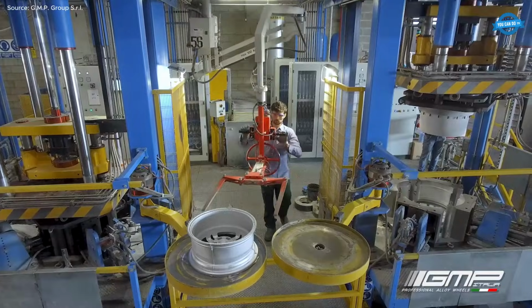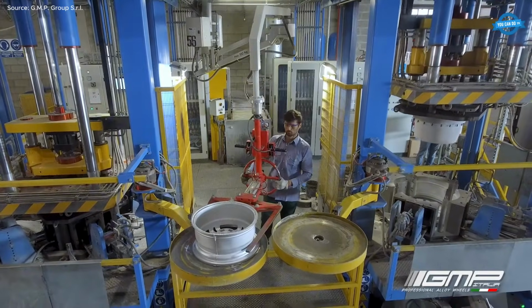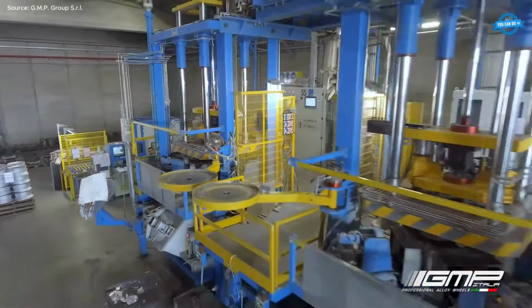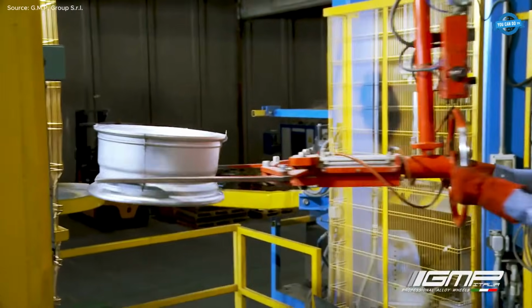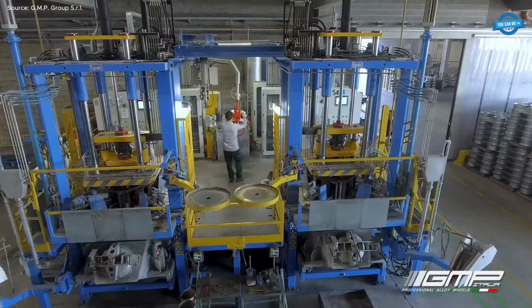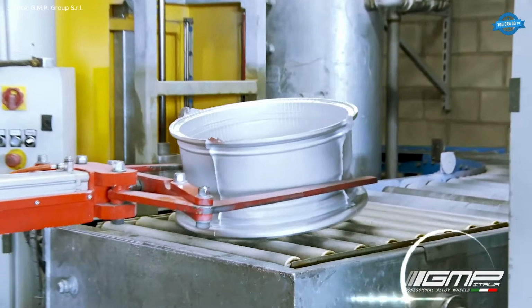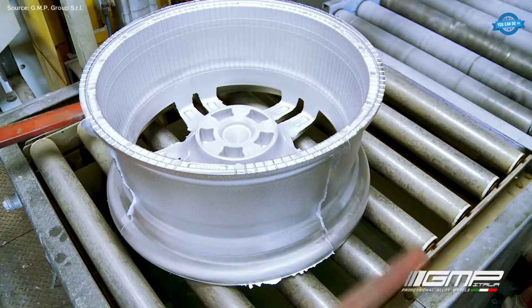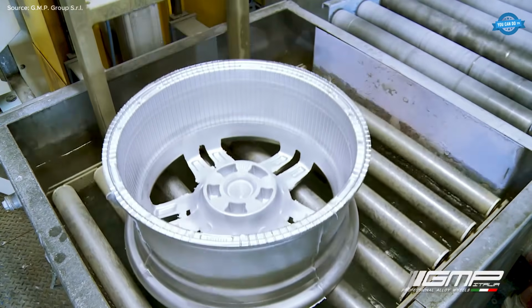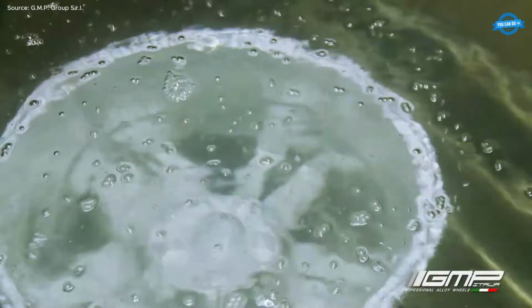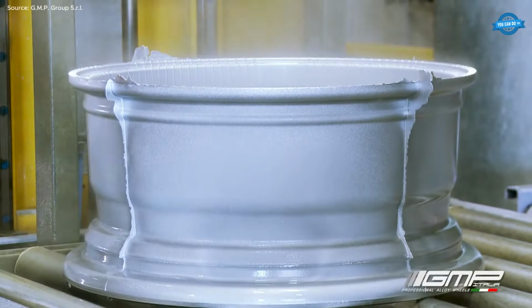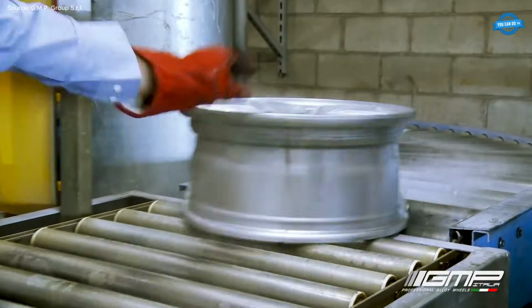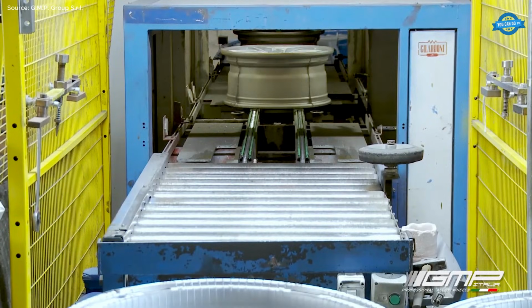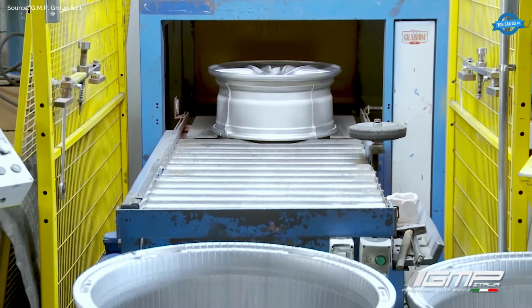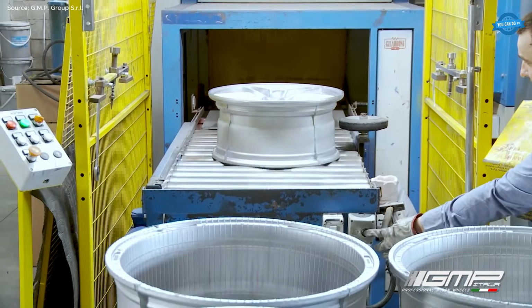Once the casting solidifies, each wheel is robotically extracted and routed through CNC machining centers. Here, automated lathes sculpt the rim profile, mill the hub interface, and establish exact geometric tolerances. Dimensional accuracy is verified through coordinate measuring machines and laser scanners that inspect surface flatness, concentricity, and spoke symmetry. GMP technicians then conduct X-ray analysis to detect internal defects before moving to shot blasting, pre-treatment, and multi-layer powder coating. The result is a wheel engineered for performance, durability, and unmistakable GMP craftsmanship.